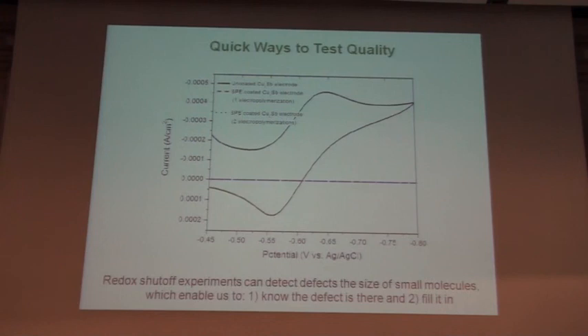To test the quality of this coating, we needed to develop methods that were very fast, that could let us know that our layer was perfect before going on to the last step of adding the cathode material. So what we do is we put a very small molecule in solution that has well-known electrochemical activity. So if you scan voltage and measure current, the molecule gives a signal that looks like this. Once you're coated, there should be no signal at all. We call this redox shutoff. This tells us that the coating is perfect, and then we can go on to the next step. If we see any signature of this molecule, we know there's a defect somewhere. We don't need to know where it is, we just need to know it's present. We can then put the electrode back in the monomer solution, pulse one more time, and in that way we've been able to basically demonstrate the first true 3D battery that actually stores charge and that doesn't leak current.